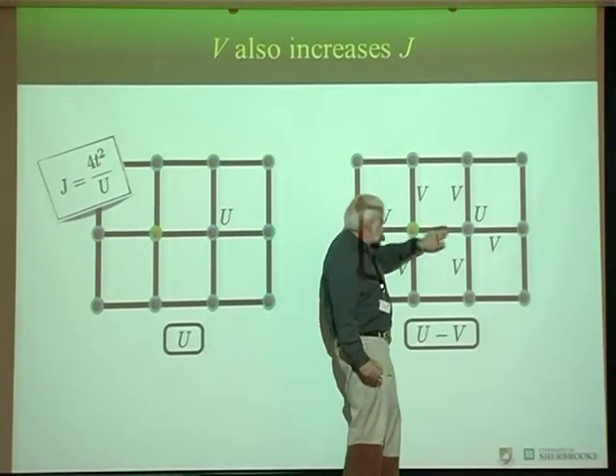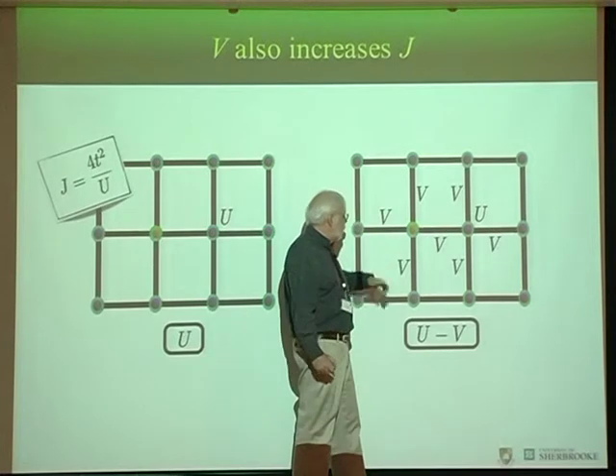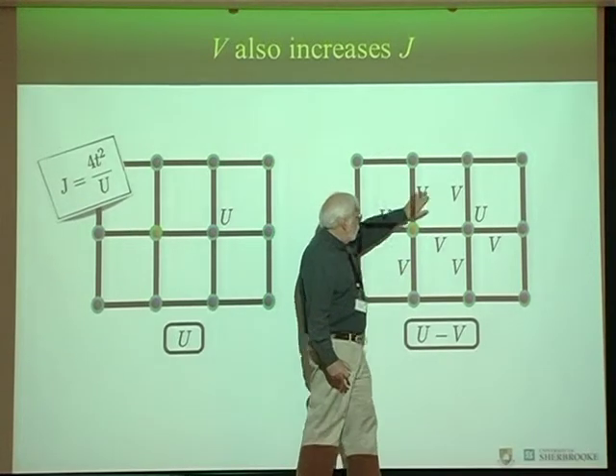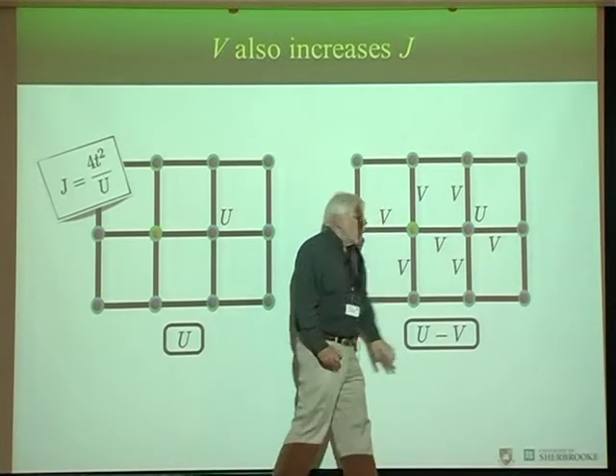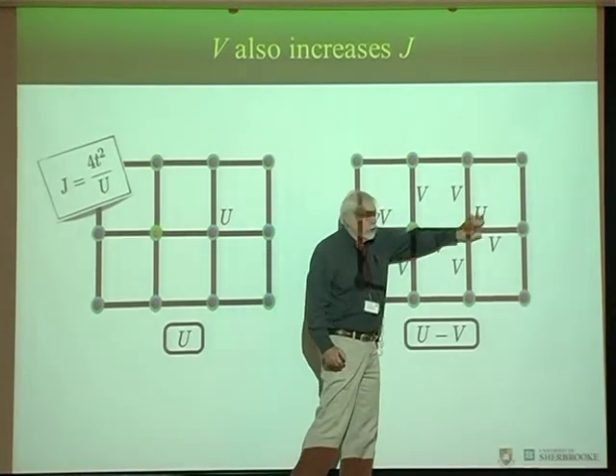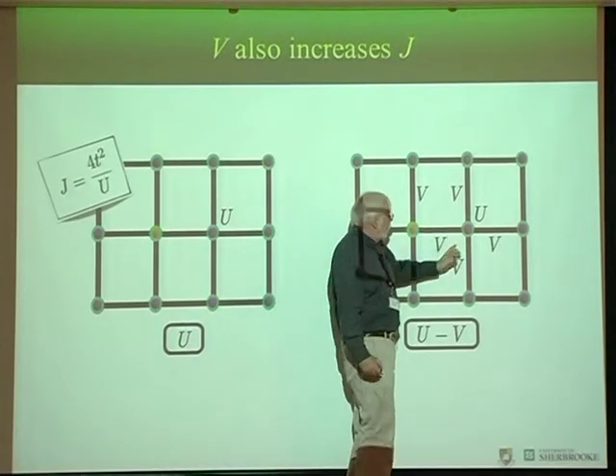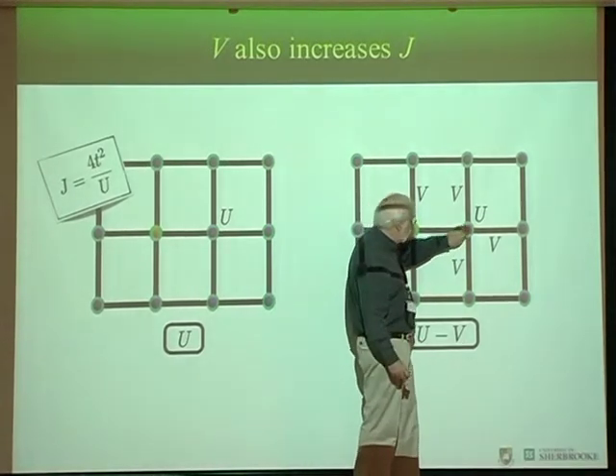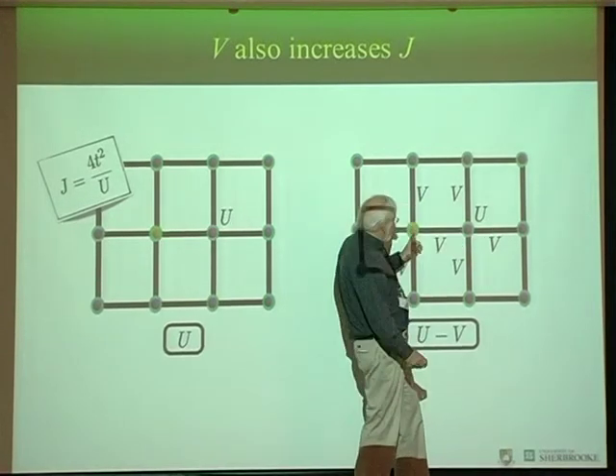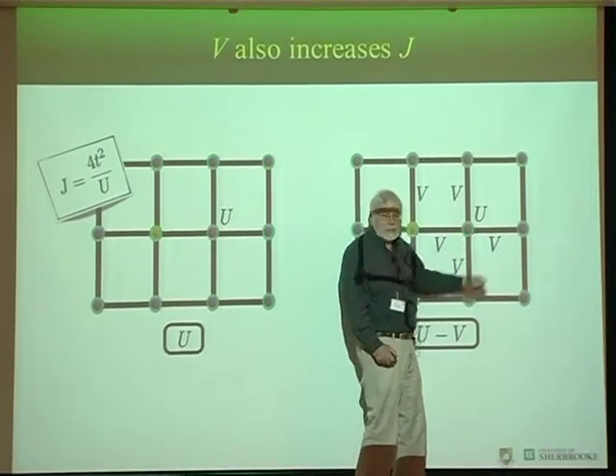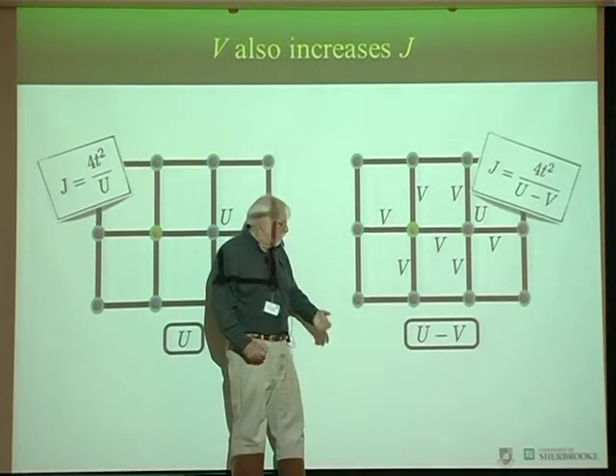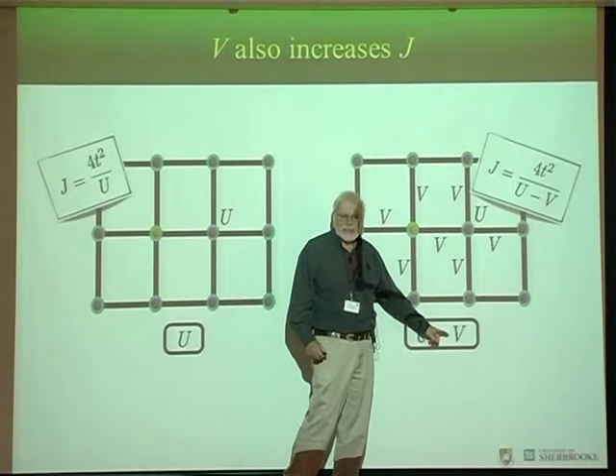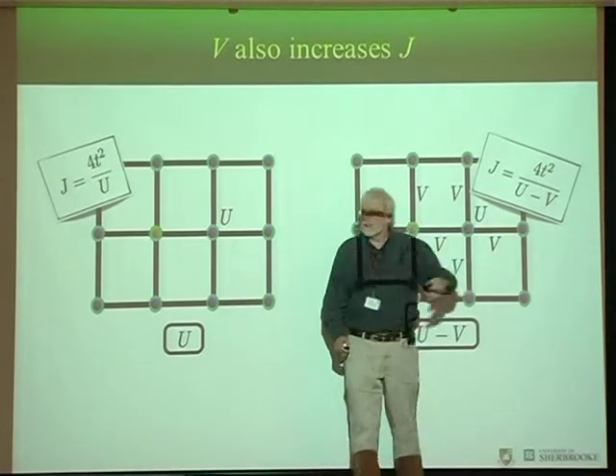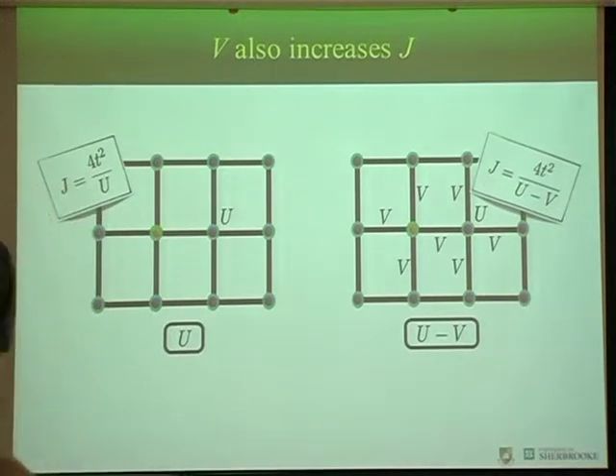Well, if I have the two electrons here at their original positions, then there are 7 V's that come in. Now, if this goes there, there's an energy cost that is U. But now you have only 6 times V because you have these three V's, and then the extra electron has also V, so it's 6 times. So in fact, V reduces the energy denominator. So J has increased by putting V. So V is not only repulsion. When you have this possibility of having a J, it's also attractive.